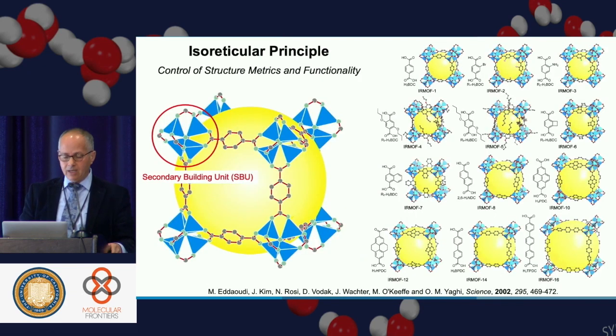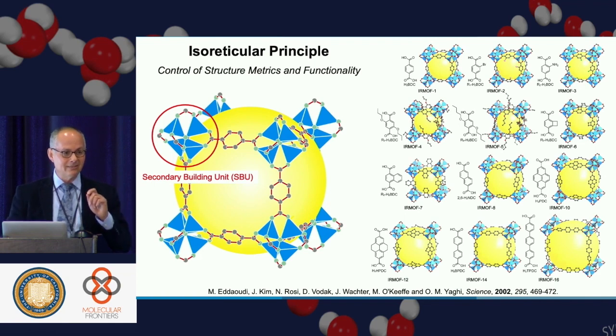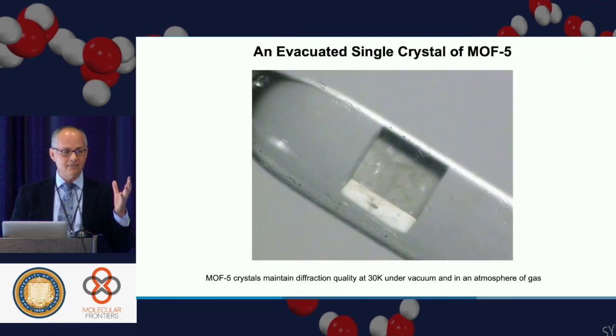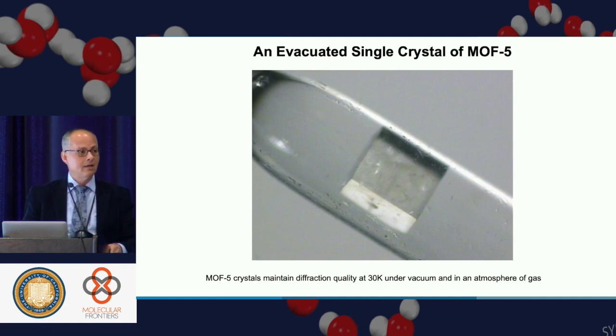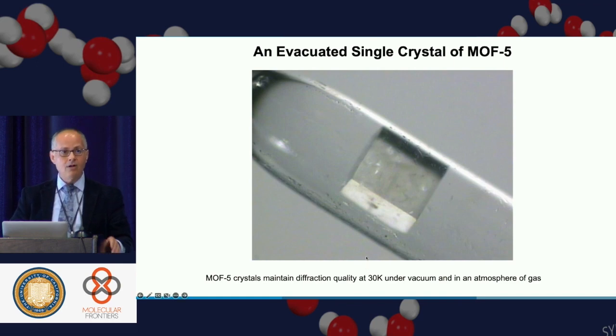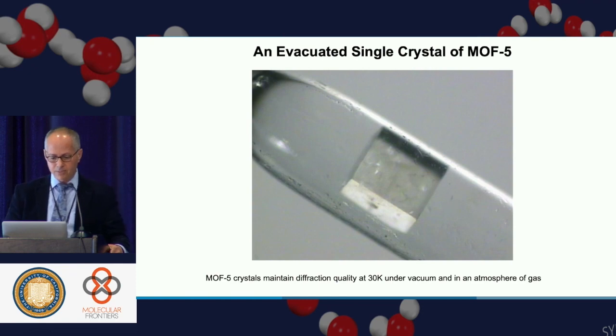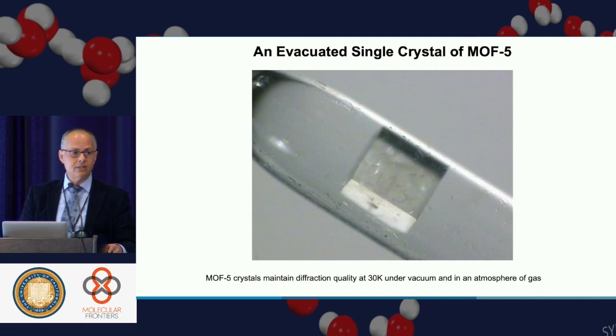So I said that every atom in these structures is an adsorptive site, but I didn't show you evidence of that. So now I'm going to show you evidence with an almost impossible experiment, which was to take this MOF-5 structure. Remember, I said 61% of the structure is just empty space, and you evacuate it, you put it in a capillary for X-ray diffraction, you cool it down to 30 Kelvin. Almost every crystal you know will not maintain its monocrystallinity, will be rendered useless in X-ray if you cool it down to 30 Kelvin, because they will crack, especially porous materials. And so this was a very first-time success to analyze the structure where the pores are empty, and now you have just the framework.